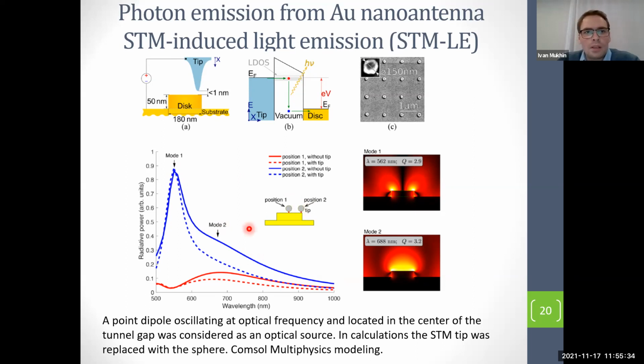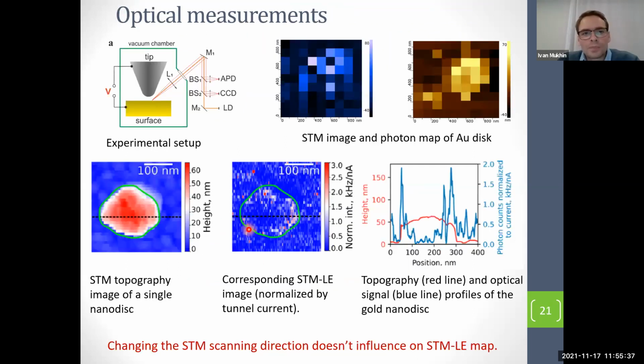So we have the same UHV STM chamber. This is a low resolution STM image and a simultaneously acquired optical image associated with photon generation. And you can see that the nano-antenna enhances the optical signal compared to the metal substrate. You remember, they have a metal substrate and a nanodisk. So we can clearly distinguish an antenna position via the STM image and via the optical image. Okay, so we can enhance the optical signal.